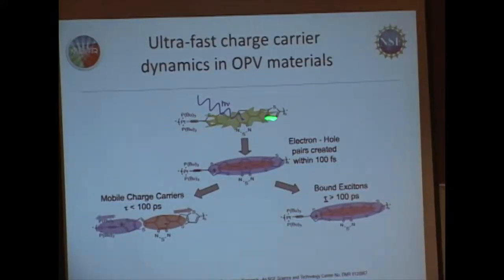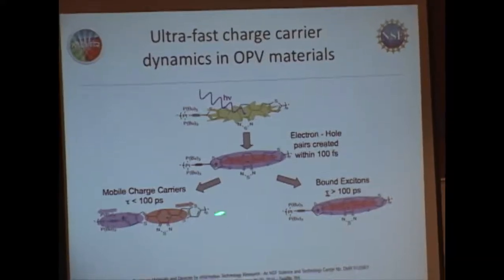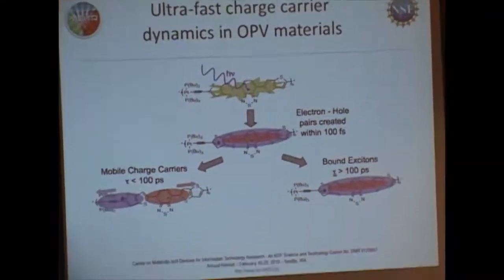And this little cartoon shows what we think is going on here: you excite the material, you create some electron hole pairs, and then something could happen. This process occurs in a very fast time frame, maybe 100 femtoseconds. Really quickly after that, sometimes some of these carriers are separated, and that's what's good, and that's what happens in the external circuit for creating photovoltaic. And after this process, there's some bound excitons that can occur. The interesting thing about the terahertz spectroscopy is we can tell the difference between these two states, between charge-separated states and between these bound excitons because of the nature of their photoconductivity.